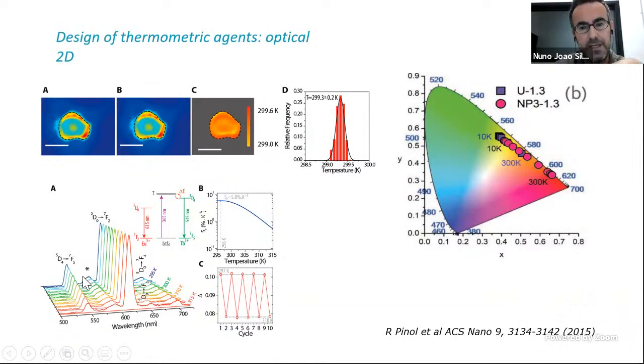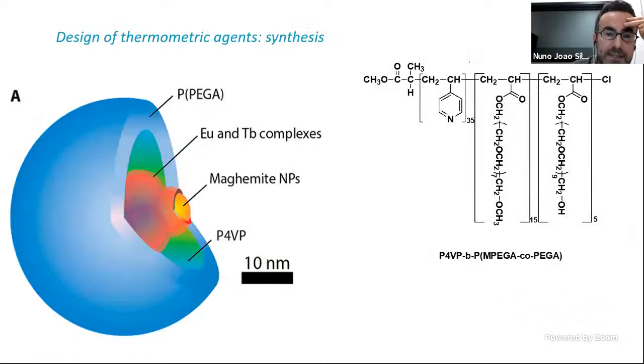And based on this relative change, so basically the color, if you want, the color was changing from this yellow here to this red here. And so by measuring this color in an optical microscope, we were able to measure the temperature of a cell, and we were able to spot inhomogeneities. So inhomogeneities in temperature across the cell membrane here. So we got into the second dimension of measuring heat.